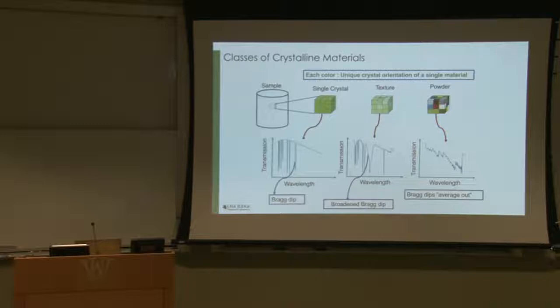If it has some texture, which means it's not a perfect single crystal, you get something like this, but with broader peaks. Whereas if you look at a powder, which basically means that each of the sub-regions of this little region is oriented with a different crystal orientation, you get a pattern which looks very different. Usually when people do CT, for tomography, they're often dealing with samples whose attenuation profile looks like this and not like this, though this can be important.